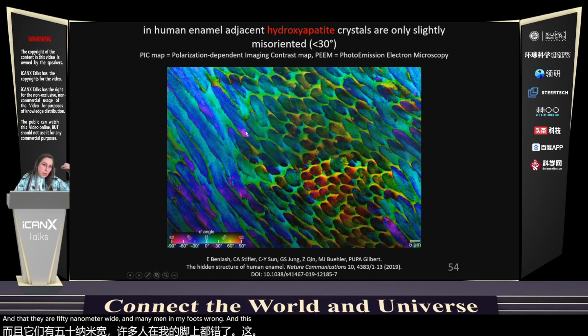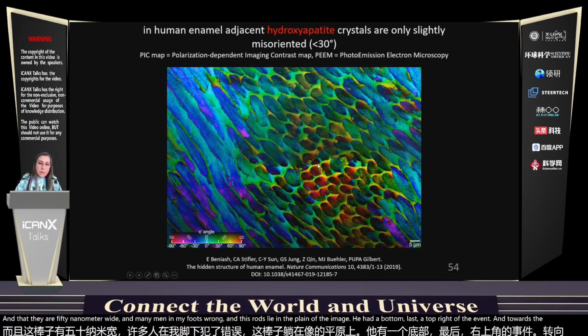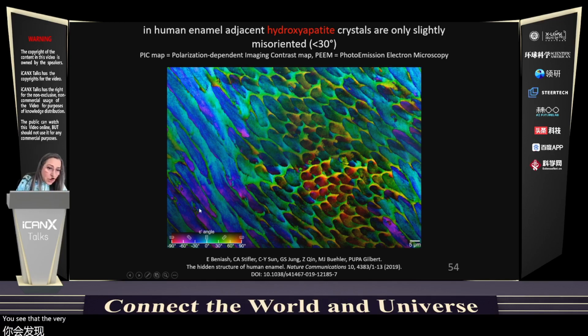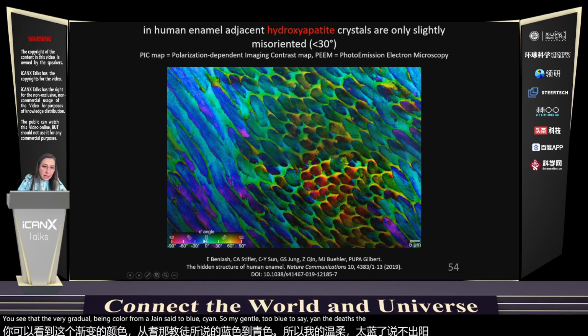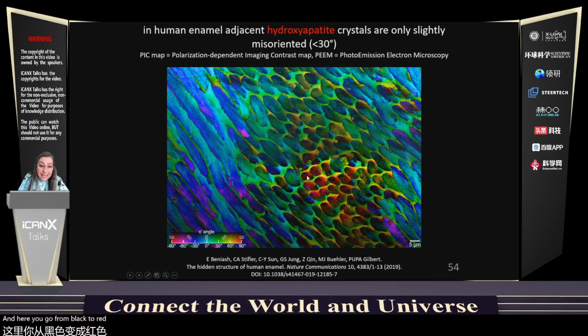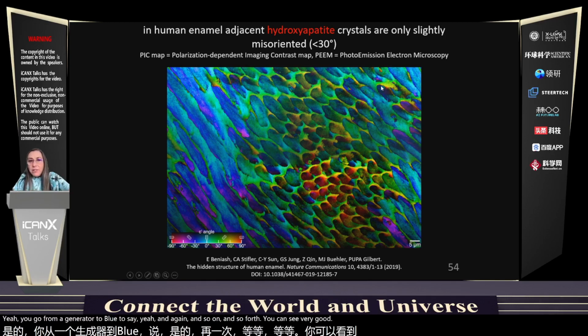And these rods lie in the plane of the image here at bottom left, at top right of the image, and towards the center of the image they're perpendicular to the image plane. You see that they vary gradually in color from magenta to blue to cyan. So magenta to blue to cyan, that's a 60-degree angle. And here you go from black to red, that's a 90-degree angle. Here you go from magenta to blue to cyan again, and so on and so forth. You can see very gradually changing